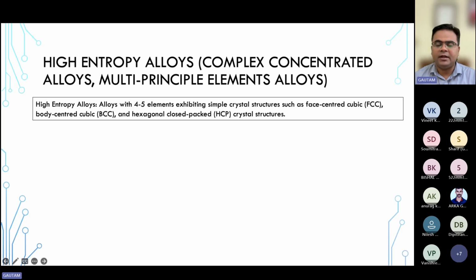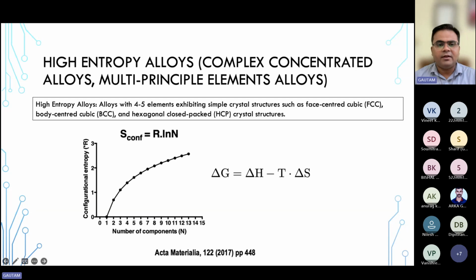That was the idea which was propagated earlier, but somehow people stumbled upon these kinds of systems where they started to form single phase solid solutions. The initial idea was that if you have an equiatomic composition, where all elements are in equal composition, then the configurational entropy is maximized, as we know from second year thermodynamics. And as you increase the number of components, N, the configurational entropy increases.